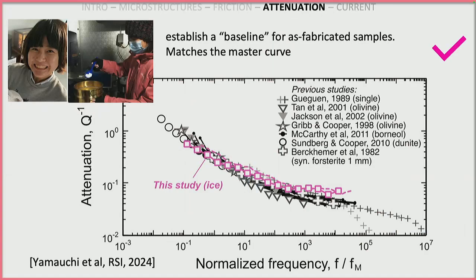In doing so, she tested as-fabricated ice samples at very low background stresses, and she was able to match this master curve, which I think is the first time we've been able to do that. It fits. So we can have that same very low stress diffusion at the grain boundary process. But that's not why we built it. We actually wanted to go to the next level and start looking at other effects. So stay tuned. She's done some really nice experiments, both increasing the strain, which adds dislocations in the material, and then taking it to a full extreme.